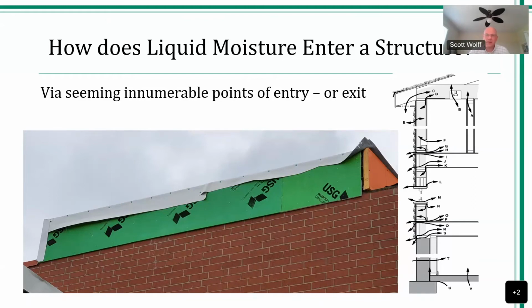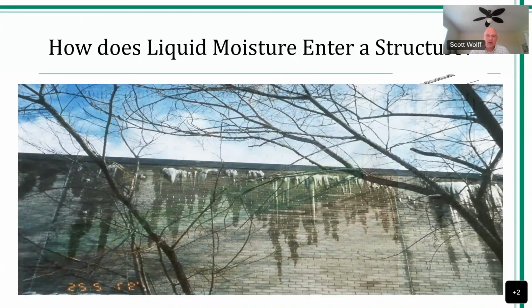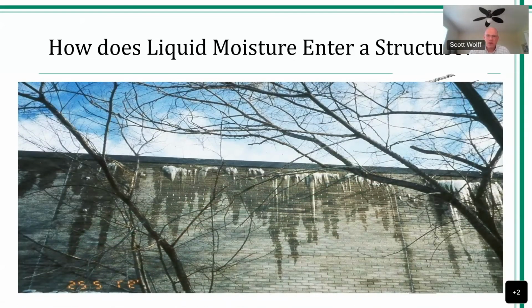In heat dominated climates, climate zones 5 and higher, typically warm, moist interior air in the wintertime scenario, because we're humidifying, will rise and find its way to the point of least resistance, which is potentially at the parapet condition. And of course, this is the ugly result: we can have substantial amounts of water finding its way to the outside. So high temperature is always going to seek low temperature. Higher humidities always seek lower humidity. They always want to seek their equilibrium. So this is why we want to make sure that we get all of these connecting points fully adhered.